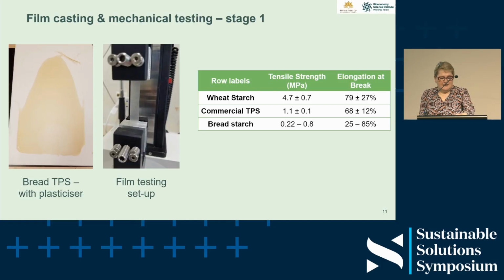So, after we'd made, just in the lab, basically mixed our extracted starch with a glycerol plasticizer, we were able to form some just on the bench, and then it was tested for tensile strength and how far you could stretch it before it broke. The wheat starch numbers are that was a native commercially available starch. Then we tested against a commercial thermoplastic starch, and then also with the bread starch. Bread starch obviously had a lower tensile strength, and the elongation at break sort of was variable. But it looked like we might be able to make what we wanted to.